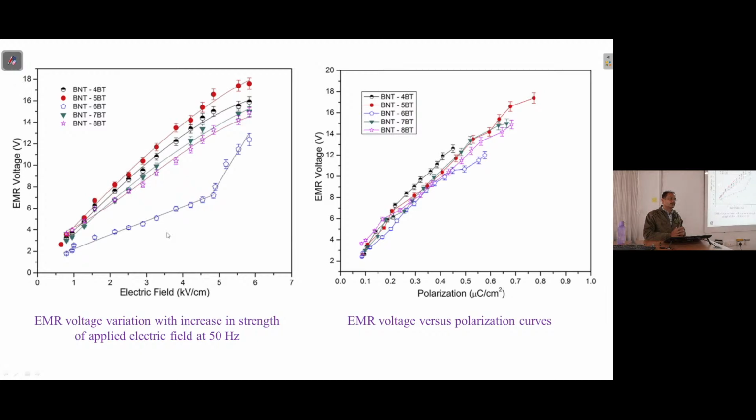Phase boundaries always offer resistance, like, at least for grains you must have considered this, right? From a mechanical point of view, strength is higher when you have smaller grains, right? Anybody from mechanical will be familiar with it. That is so because grain boundaries offer resistance. Similarly here, phase boundaries will offer resistance when we try to polarize.